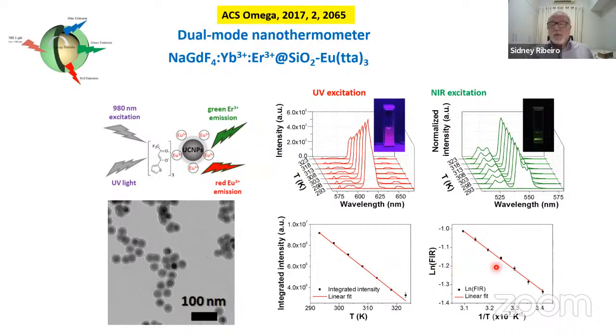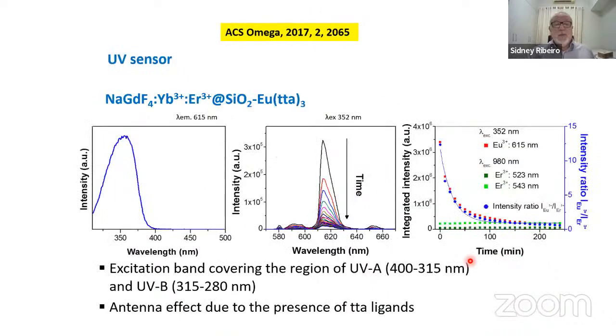So you have here the two plots obtained from the data of these two systems, showing that you can measure the temperature in two different ways. If you increase the UV power, you will start to degrade this organic ligand that is bonded to europium. And so what you observe in practice is the decrease of the europium emission intensity with the increase in the UV power.